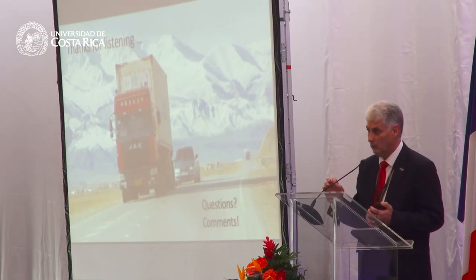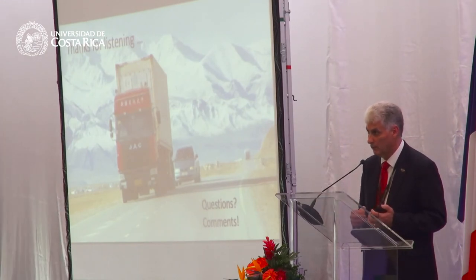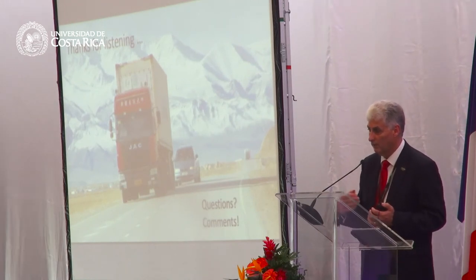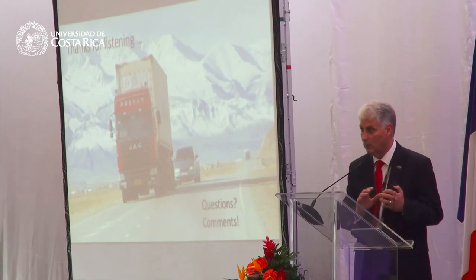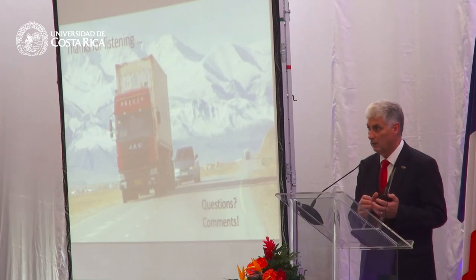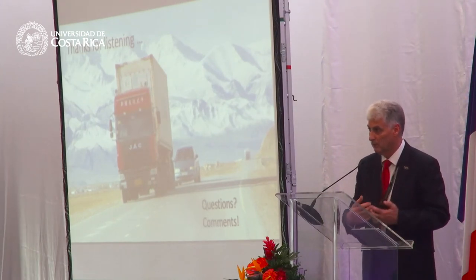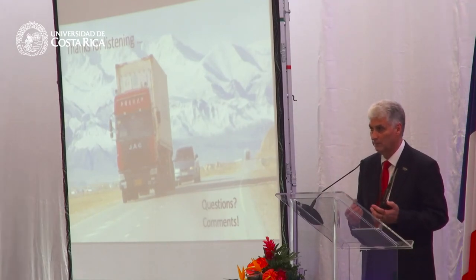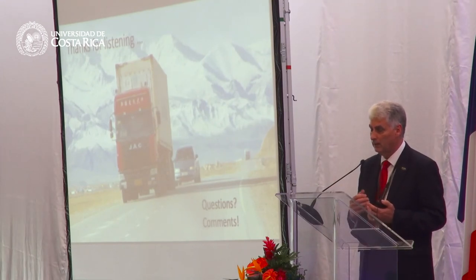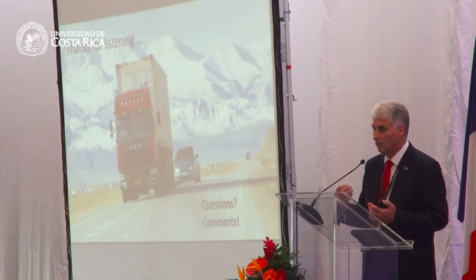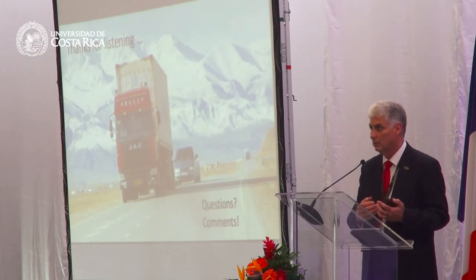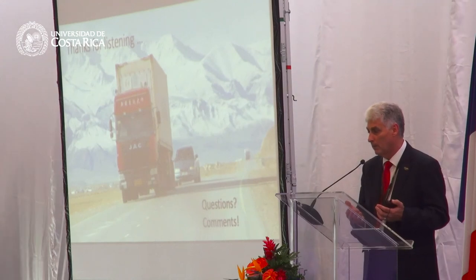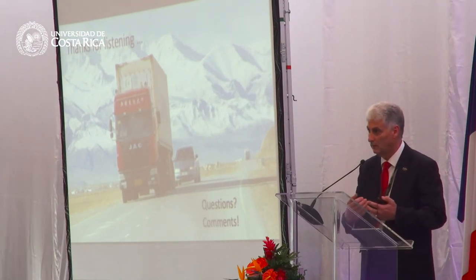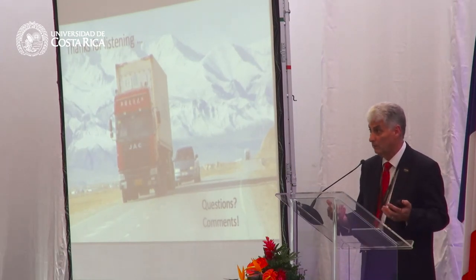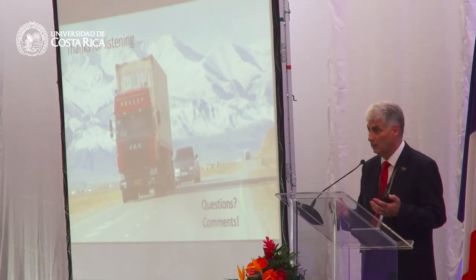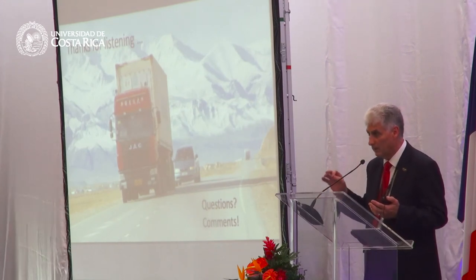What we don't know yet is how to apply those parameters in a climate like Costa Rica. Our validation work and the efforts looking at those parameters showed that those parameters work very nicely in a climate like Pennsylvania. Now, when we take the material properties and translate that through to Costa Rica, we have a very different climate. So if we use those parameters here, and there's nothing that would say to me that those parameters should not work, but we will need to consider local calibration. So I think we need to look at areas where we have durability issues in Costa Rica, and then see if we can change the numbers, or even see if the same numbers work. But I would expect there to be some differences in the numbers from the USA to here in Costa Rica.